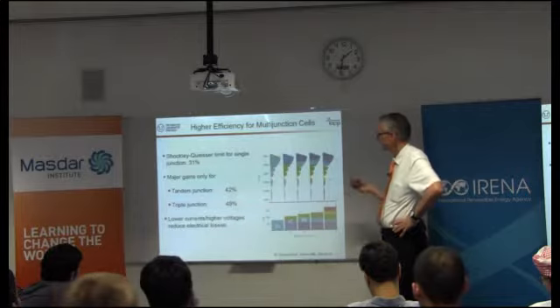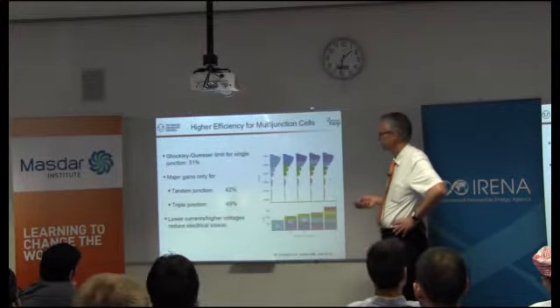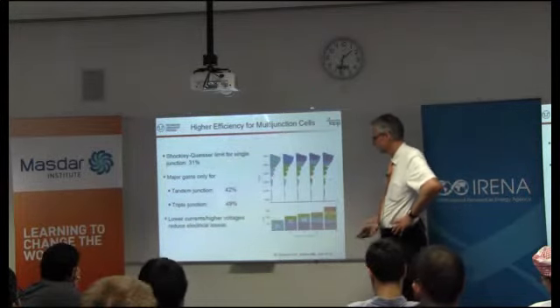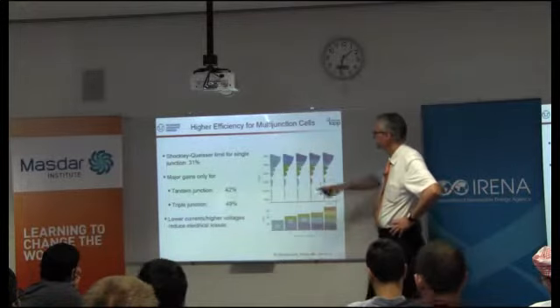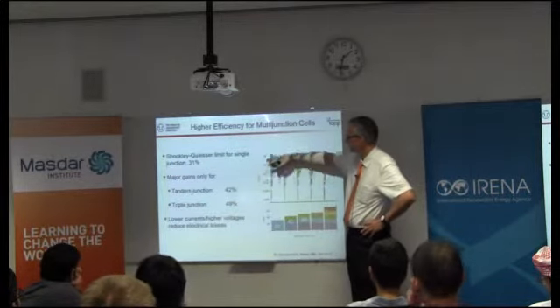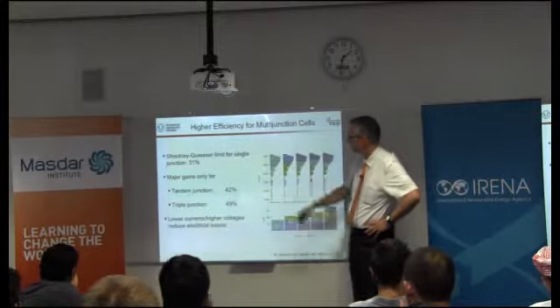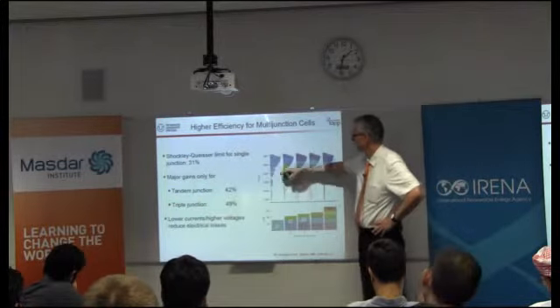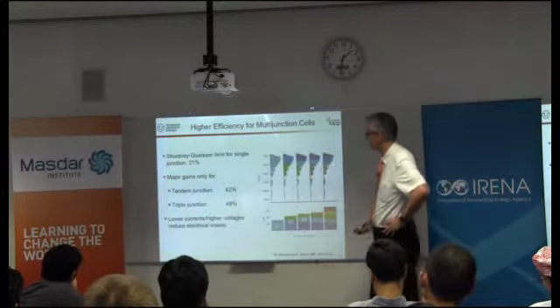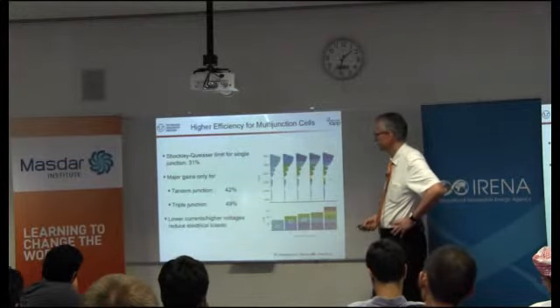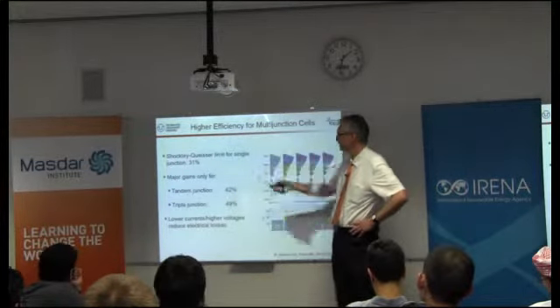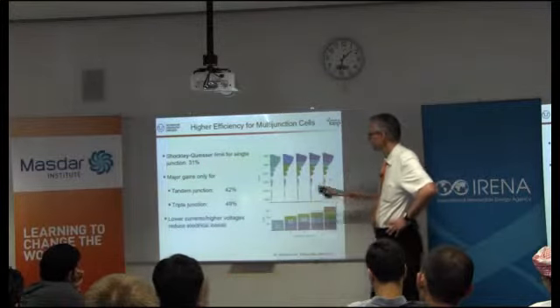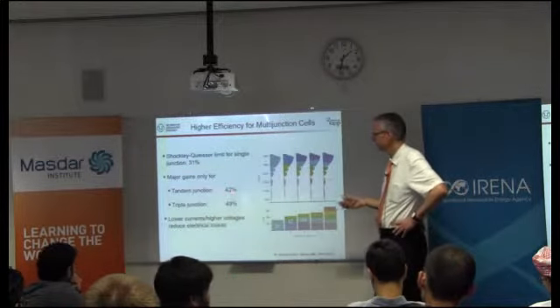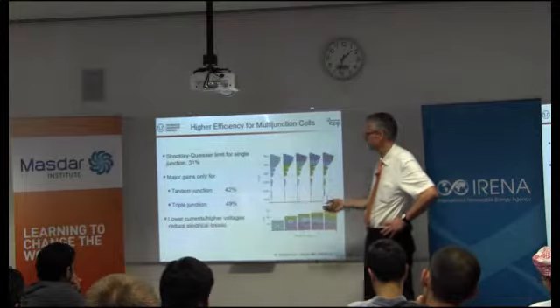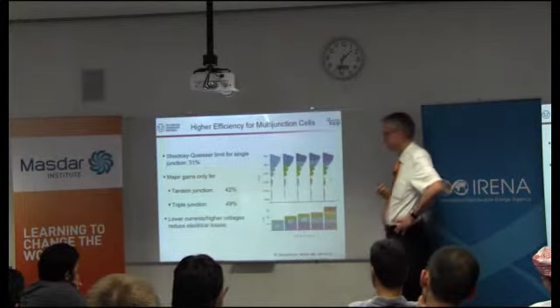So the way to go is then, as you know, to go to multi-junction. This is a graph I took from a recent paper of Michael Gratzel. If you have a single junction device, you harvest the spectrum, but in the higher parts you lose a lot of energy. And if you divide it in 2 or 3 or 4, you can increase the potential efficiency. The Shockley-Queisser limit for a single junction is 31. If you do 2 junctions, a tandem, 42. If you do 3, 49. If you do infinity, 85.